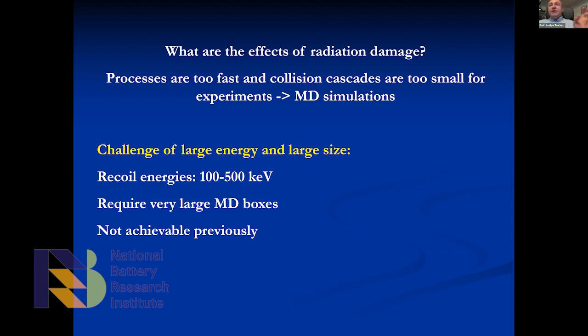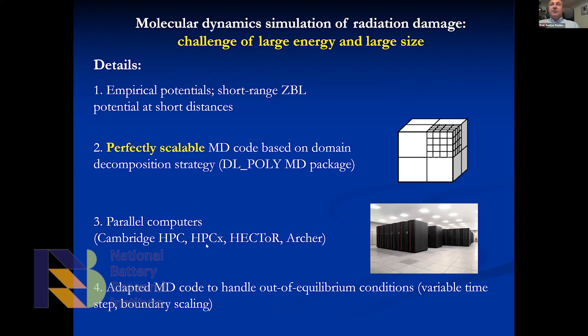and in particular, in actinides, most of the damage comes from alpha decay, and so recoil has an energy of about 100 keV. There is also a small alpha particle flying the opposite way, but that alpha particle has a small cross section, so we don't need to worry about it too much. The primary damage comes from that heavy recoil, which has a high energy of 100 keV. Now that's 100,000 electron volts, right? And that's quite a high energy. So we need a large box to simulate the system. Right, so I talked a little bit about potentials.